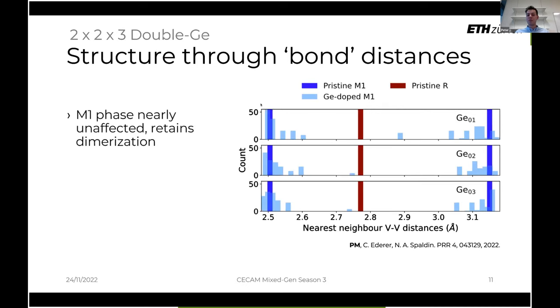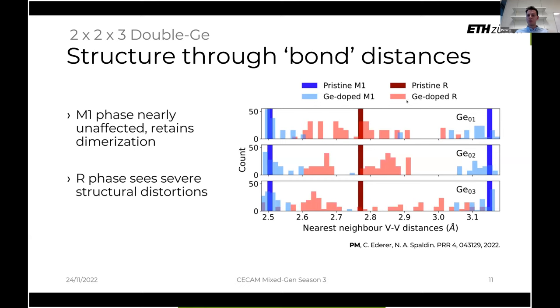After the addition of germanium, we now see the following. The monoclinic phase still retains this dimerization pattern, but becomes distorted. We have a Gaussian distortion around these peaks, which still remain the most likely bond distance to occur. However, in the rutile phase, the story is quite different. After the addition of germanium, we now have this light red color, where we see that the vanadium-vanadium distances become completely disordered. In all the different configurations, we see a wide variety of different bond lengths that one obtains after geometry optimization.